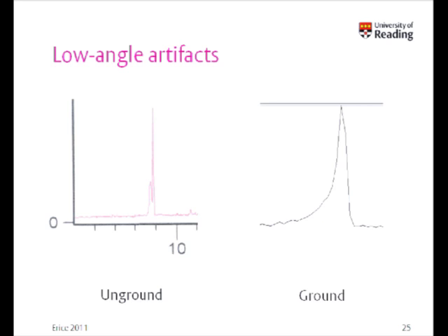So Mark, the PhD student at Reading, collected the data. We saw exactly the same thing, but then he reported that the material looked rather sparkly, and should he grind it? I said, yeah, give it a grind and recollect. And mysteriously, this peak completely disappeared, and we're back to a single peak.